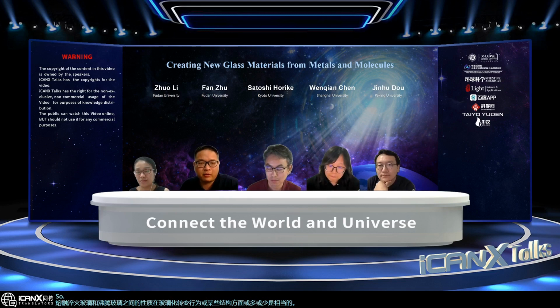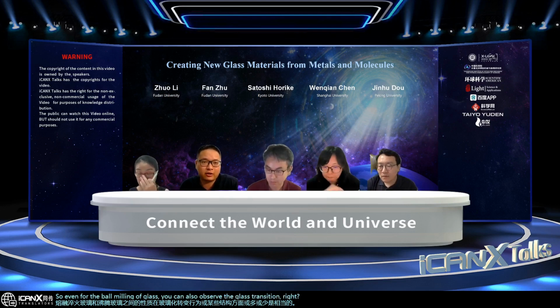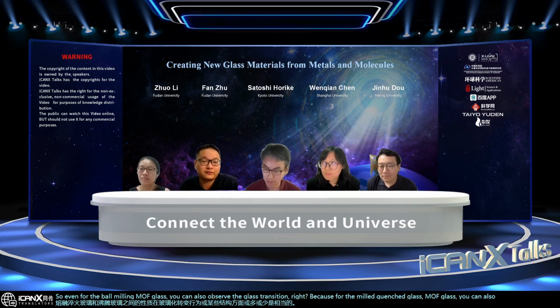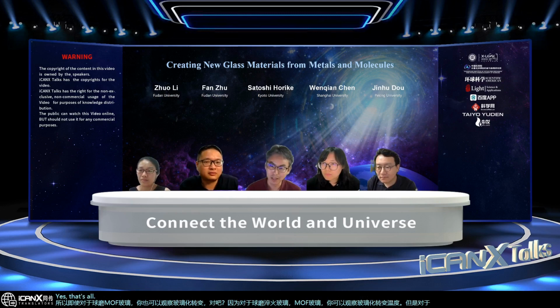So even for the ball-milled MOF glass, you can observe the glass transition, right? Because for the melt-quench MOF glass, you can observe the glass transition temperature, but for the ball-milled one, you can also observe such a phenomenon, right? Yes, for glass scientists it's kind of surprising, which I often hear. Even for the ball-milled glass, we could see a very clear glass transition.